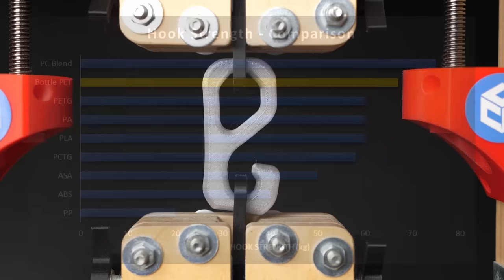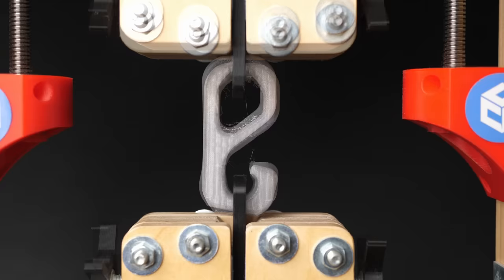Again, no sudden break, but rather a slow yielding. Layer adhesion on the standing hook wasn't impressive, the part failed at only 16 kg.